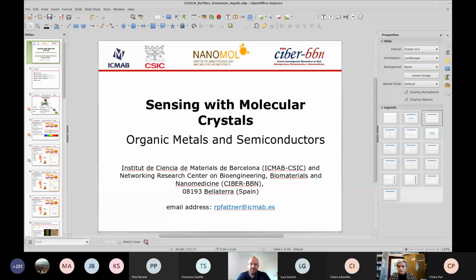Okay, thank you. The second question: molecular materials are known to be structurally anisotropic. Is this the same for the sensing response? In other words, is the sensing response affected by the crystalline orientation? Yes, of course it is. And I did not go into detail in this case, but what we actually have is that they are very well ordered perpendicular to the surface, but they are randomly oriented in AB, right? So we have a random superposition in AB, and this makes the deformation response anisotropic.